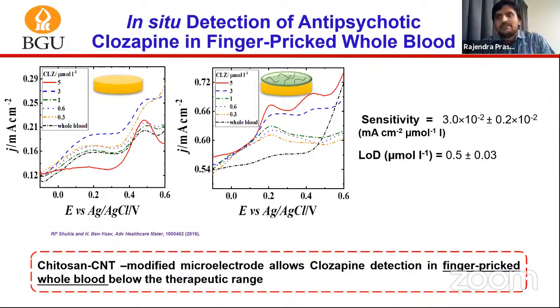After all, we had a lot of experiments, and we tested the clozapine performance using carbon nanotube modified microelectrodes in different solutions, and also in serum samples that I'm not going to show. I'm just showing you here that we detected the clozapine in 20 microliter volume of whole blood, which was spiked with different clozapine concentrations. The first figure shows you the detection with bare. Here you don't see any dose response. The bare microelectrode was not able to differentiate between different clozapine concentrations because of the high complexity and the fouling effect generated from the whole blood. However, here we see some dose response at 0.2 volts, and we compared it with the buffer, and we calculated the limit of detection, which is 0.5. Again, it is below the clinical range, which is 1 to 3 micromole per liter. So this kind of microelectrode modification can be used for the detection of clozapine.